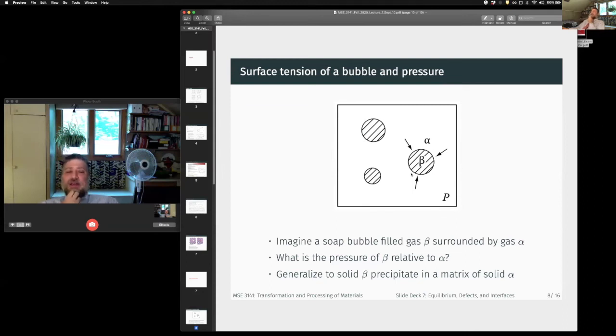They depend on the configuration of our microstructure. Let that sink in for a little bit. Our thermodynamic properties of our material are not necessarily intrinsic properties, but they depend on the arrangement in the microstructure. Right? Now you're thinking like real material scientists, not solid state chemists or physicists.